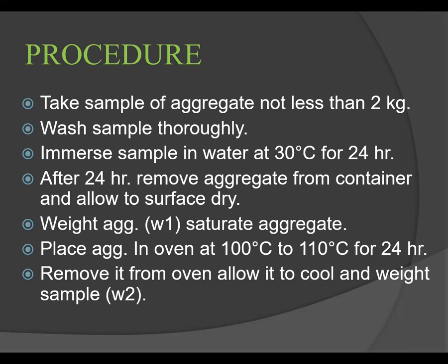Then the basket with aggregate is kept completely immersed in water for a period of 24 plus or minus 0.5 hours. That means 24 or 24.5 hours. Okay, then the basket and aggregate are weighed while suspended in water at a temperature of 30 degrees Celsius.